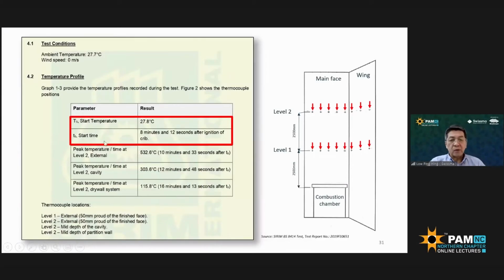Now, what is start time, the small ts? In this report, it's recorded as 8 minutes, 12 seconds after ignition of the crib. They set the fire here at the combustion chamber, and you must have consistency to do your assessment and measurement for such tests. The way they establish that benchmark is, when level two achieved 200 degrees Celsius, that's where the start time ticks. So at 8 minutes, 12 seconds after the ignition, level two registered 200 degrees Celsius. When that happens, a green light is triggered, and then the start time of the 15 minutes takes place.